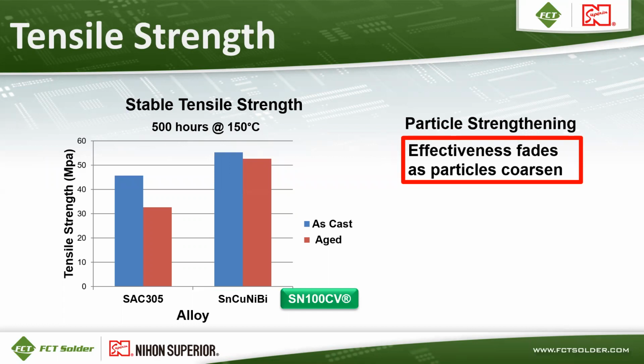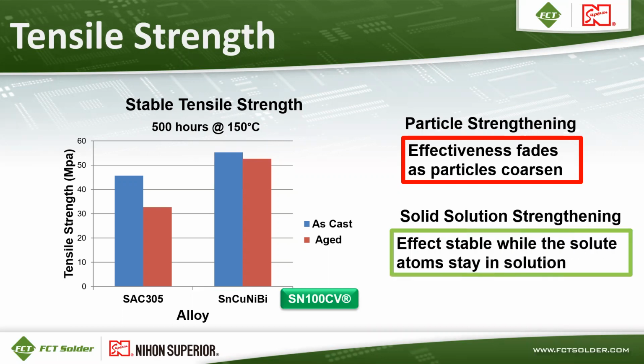That's the difference between particle strengthening, which is what SAC305 uses. SAC305 has Ag3Sn intermetallic compounds that precipitate out as particles within the solder matrix. They coarsen over time and they lose tensile strength. Whereas SN100CV has copper, nickel, and bismuth that largely stay dissolved in solid solution, and those effects of strengthening are stable. So it does not lose tensile strength with this type of aging test.